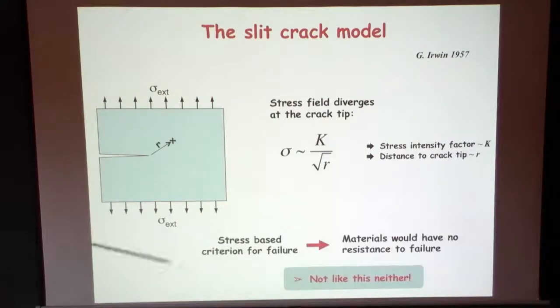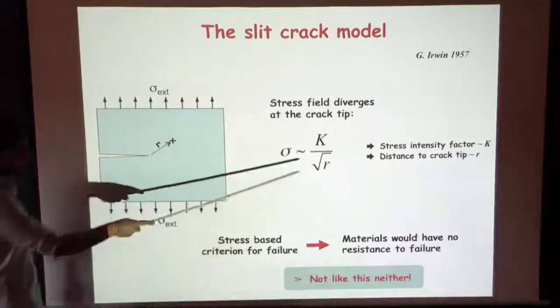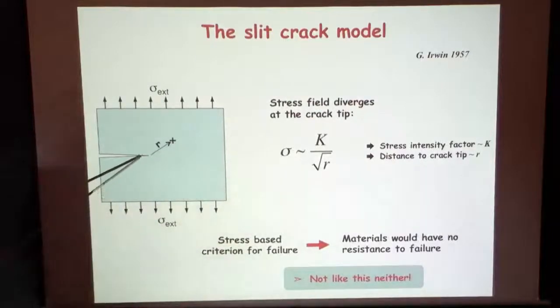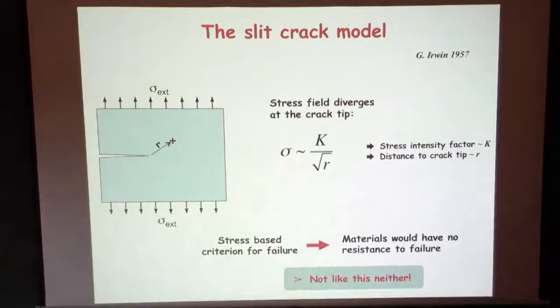So if you maintain a stress-based criterion with this kind of approach, since the stress field is diverging, you will have actually no resistance to fracture. If I apply just a little stress here, I will have infinite stress here. So I have no reason for the crack to stop growing. It's kind of a naive vision, but with this model, using a stress-based criterion, you will have systematic failure. So it's also not the correct approach.